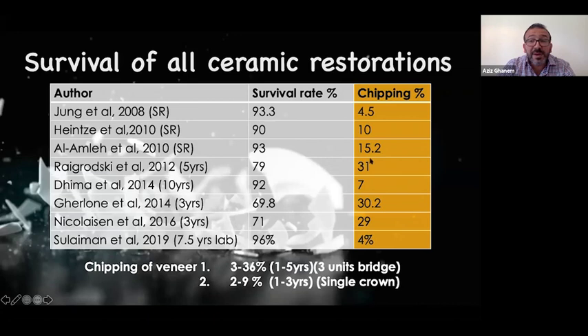chipping. However, not all of the chipped material is replaced. Basically, some of them are repaired inside the mouth. But the recommendation in the literature is just to replace any restoration with a defect, because the chipping can get bigger and bigger even if you repair it. And to make it clear for you now, because we are talking about zirconia layering, or lithium disilicate layering, the zirconia layering,